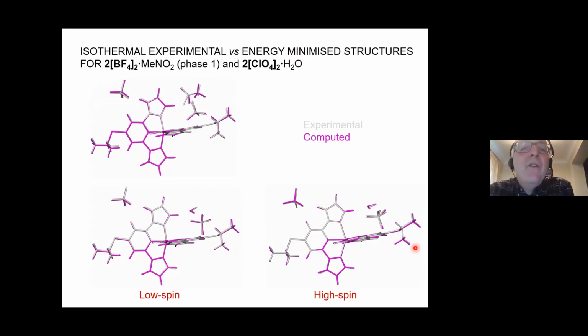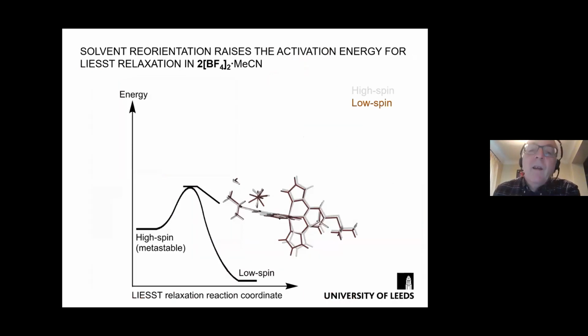So how do we interpret this? The way I interpret this is that this is telling us something about the light-induced relaxation of these compounds, which is a kinetic effect. So we have a material which is trapped in its metastable high spin state. It wants to relax to its low spin, but it has an activation barrier to overcome.